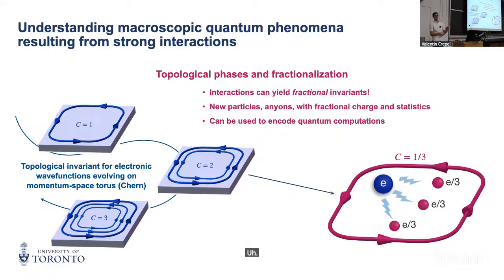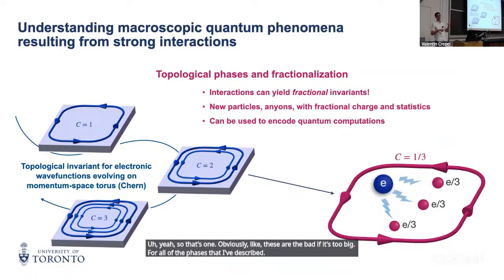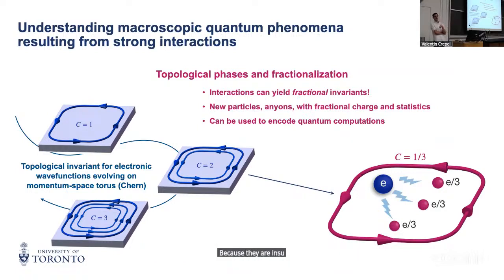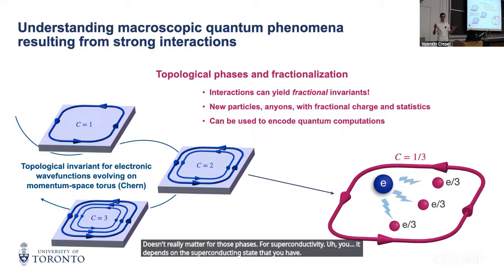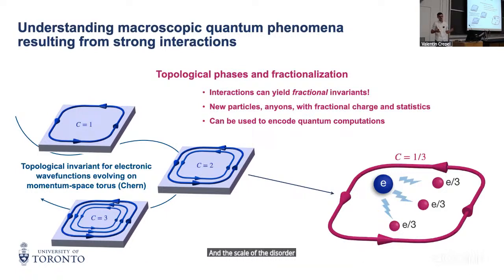Obviously, disorder is bad if it's too big. For all of the phases that I've described, disorder is usually not too bad because they are insulating for charge 1e excitation. So everything that carries charge or can be trapped in the defect doesn't really matter for those phases. For superconductivity, it depends on the superconducting state that you have and the scale of the disorder. If it's an S-wave superconductor, we know that disorder is not too bad for those kinds of superconductors. Okay, thank you.